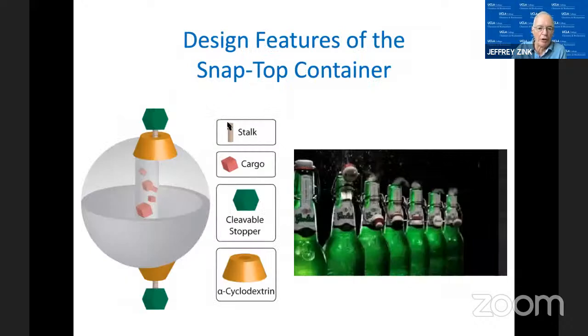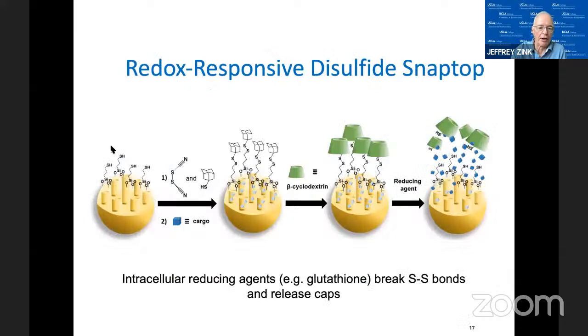The second one that works very beautifully is what we call a snap-top. The original one was based on the kind of capping a Grolsch bottle has, where some kind of stopper holds a plug in place. So this again is a cyclodextrin that's held in place by a cleavable stopper. And when that is broken off, like opening the bottle, the cap comes off and you can release the drug. Now, a much simpler way of doing that is to break the stalk directly.